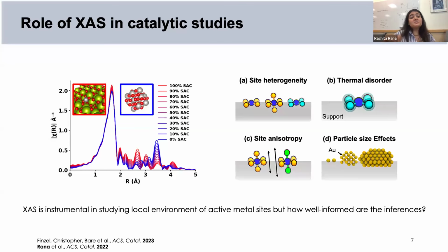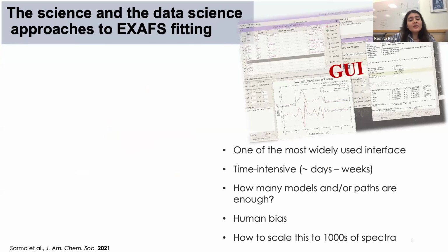Specifically, when you're talking about understanding reaction mechanisms and calculating your energy barriers using these structures that you interpret from your EXAFS results, it really becomes challenging, because there's a question about site heterogeneities, there's a question about anisotropic effects and particle size effects. And so there has to be a more consolidated way of understanding these materials and to overcome those caveats, especially when you're talking about well-defined materials that are not as complex to model.